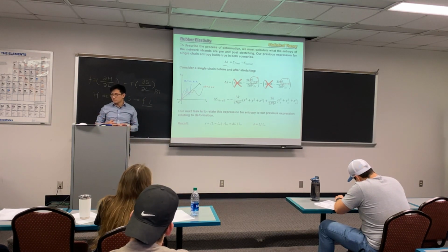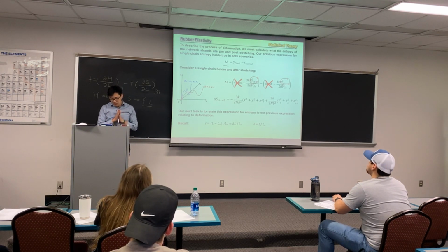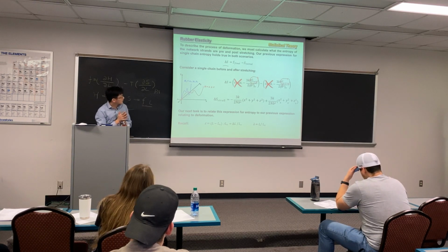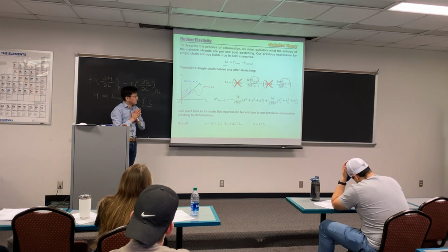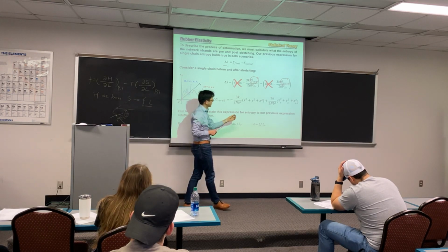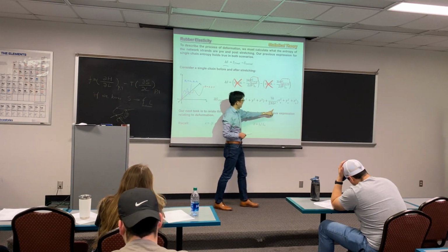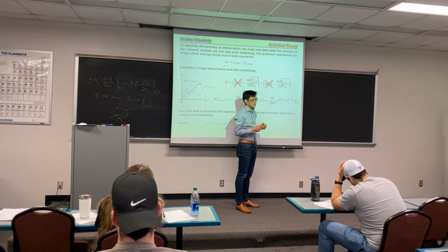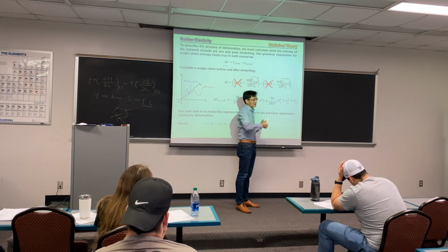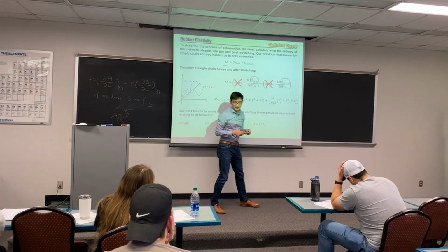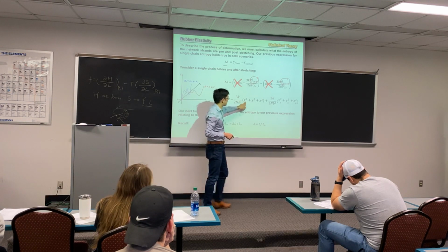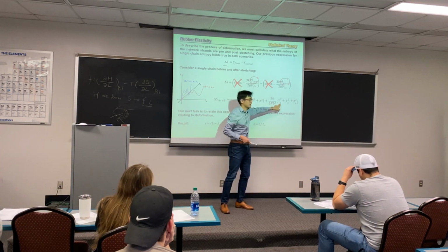Pretty straightforward, right? And recall at the beginning, we also had an affine network assumption. The affine network assumption will allow us to link the x value and the x0 value. Because of the affine network, we know if we deform the sample in a draw ratio of lambda, we can calculate what would be the x versus x0.